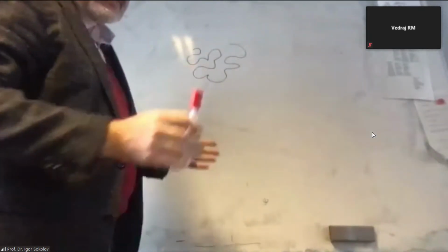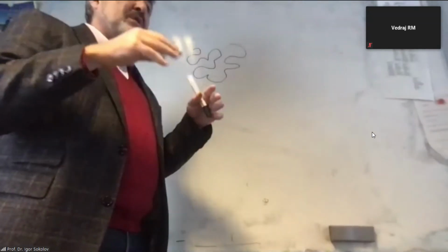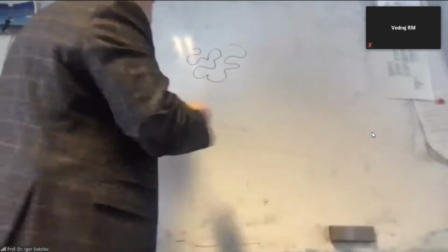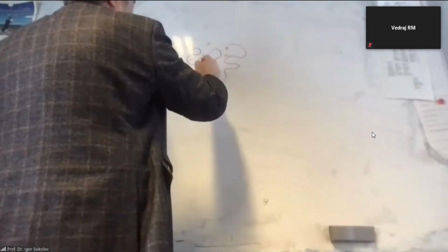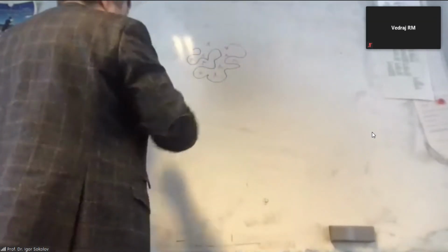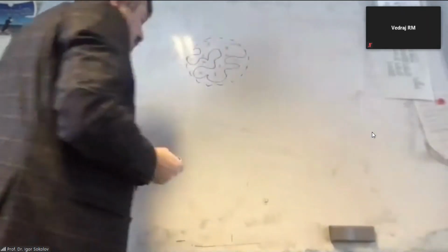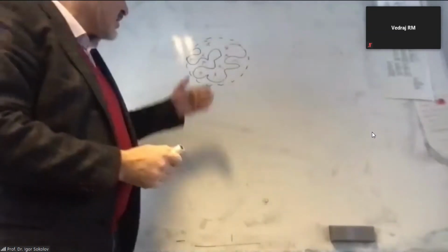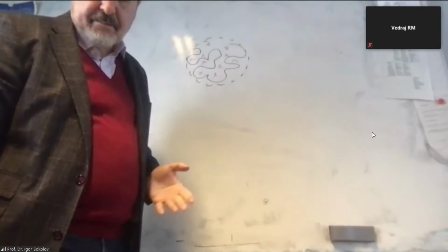It's an explanation, not a calculation, or something from which you can start a physical theory, but we said there are solvent molecules, and this thing is like a bag of monomers. In the bag you have monomers, and they exert osmotic pressure on the bag, which means that the bag gets larger, the chain gets swollen, the chain swells.